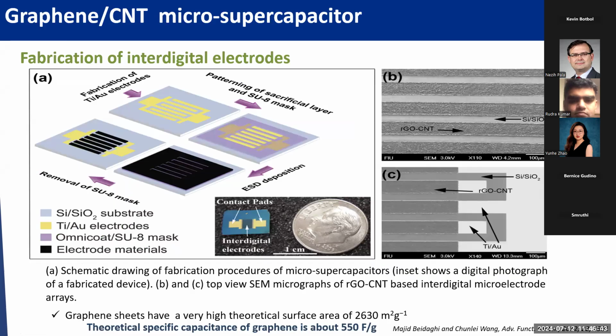So another work I want to give you a brief introduction to is graphene CNT. Graphene CNT is a material we have been working on. The first graphene CNT work was done by my first PhD student, Majid. He basically made an on-chip level, two-dimensional interdigital array. In this system, we use titanium gold as a current collector, and we use SU8, which in this case is just a shadow mask. Then we can deposit graphene CNT composite directly by electrostatic spray deposition on the entire wafer, then do the lift-off process.